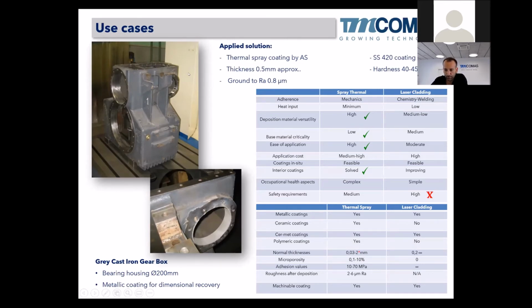The applied solution here was a thermal spray coating by arc spray, 0.5 millimeters thick. Then it was ground, machined to achieve a surface roughness of 0.8. We used a stainless steel coating with a hardness of 40-45 Rockwell. Why did we choose these thermal spray coatings? Well, mostly because we can spray inner coatings. It's an inner surface, as you can see here. It's easy to apply.